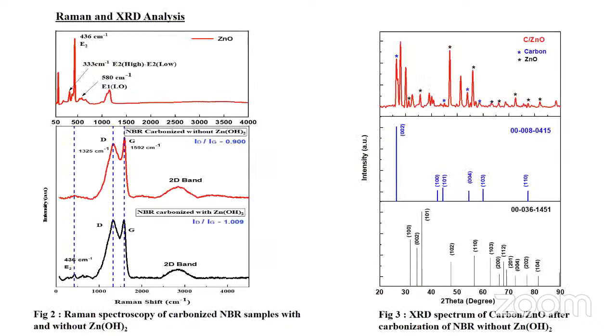In the Raman and the XRD analysis, two significant peaks related to the D and G peaks can be seen in both Raman spectra of the carbonized sample with and without zinc hydroxide. Additionally, a characteristic peak related to the E2 high vibration mode of the zinc oxide hexagonal phase can be observed in the carbonized sample with zinc hydroxide around 436.